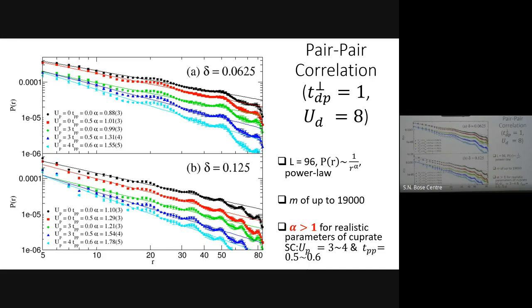There are people in DMRG who use this M. If you look up DMRG calculations, that is usually 5 to 7,000. Ours is 19,000. You cannot do better than this. Take my word for it. This is the Luttinger parameter plot. And we find, remember, alpha has to be less than 1 to have Luther-Emery order. For realistic parameters, alpha is greater than 1.